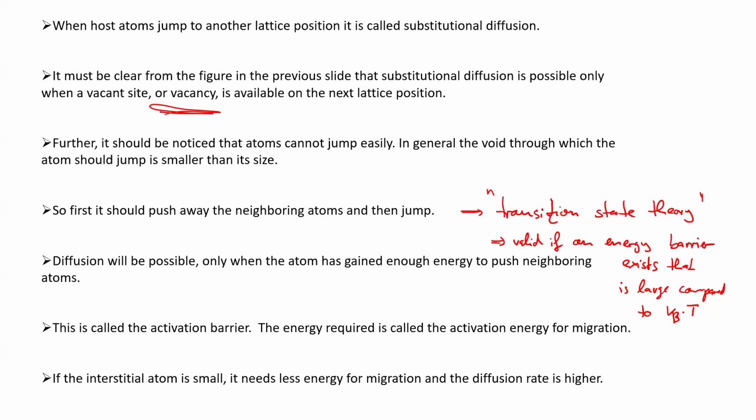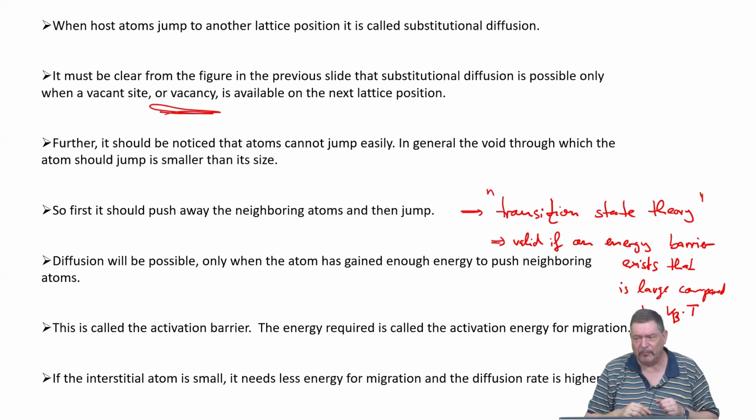For example, Poisson statistics is typical for these types of processes. So you have many, 10 to the 13, that are unsuccessful, and then one is successful. And that lifts the atom above the barrier into the new position. And that is basically underlying the description of many, many processes.